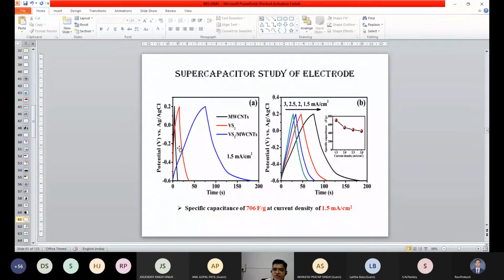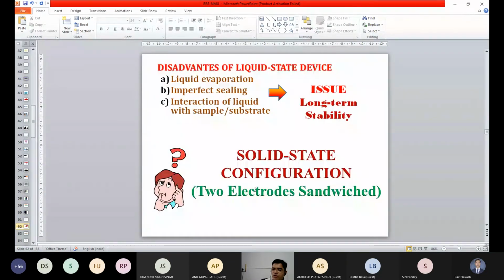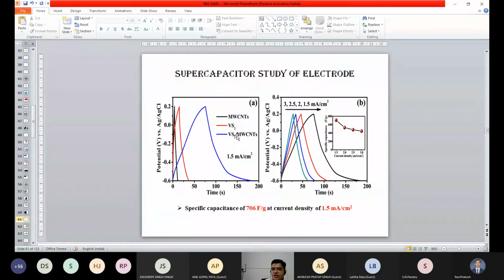Then we have also done certain charge discharge studies for this, with respect to different current densities, and we observed a specific capacitance of about 706 farad per gram. So specific capacitance can be calculated by CV, cyclic voltammetry, as well as the charge discharge study. So the most important thing is that whatever study we have performed is based on liquid, that we use liquid electrolyte. But